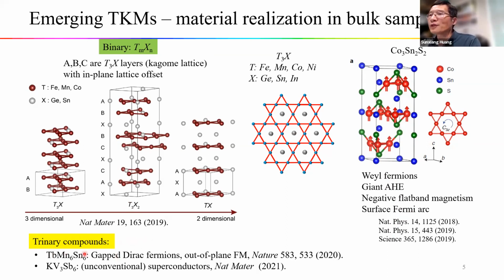So for the ternary compounds, there are the 1-6-6 structures, which are often ferrimagnets. In the case of this compound, the moment is aligned along the c-axis, which later induces this gap at the Dirac fermions and many interesting physics. For the 135 cases, superconductivity has now been observed in those compounds, and they show some unconventional behaviors.